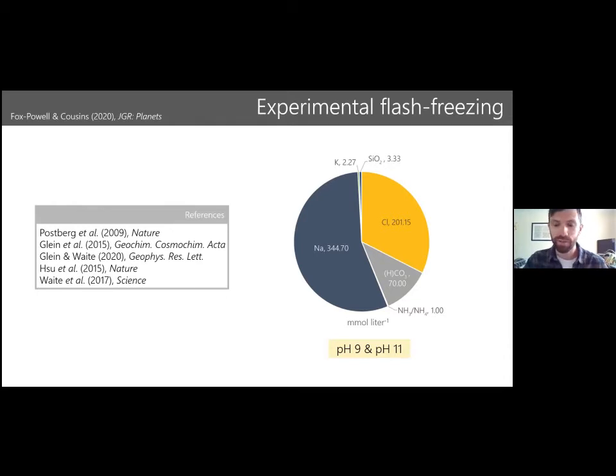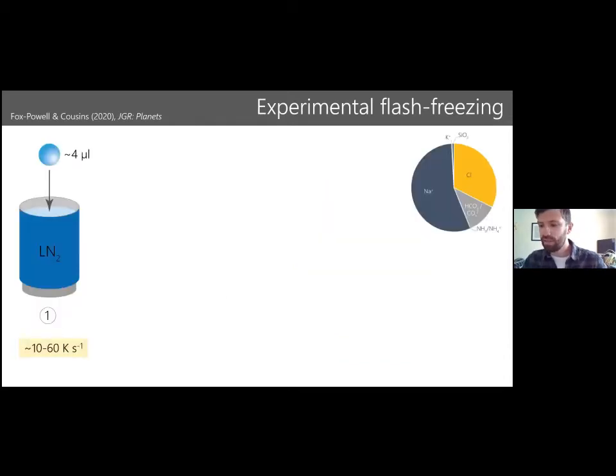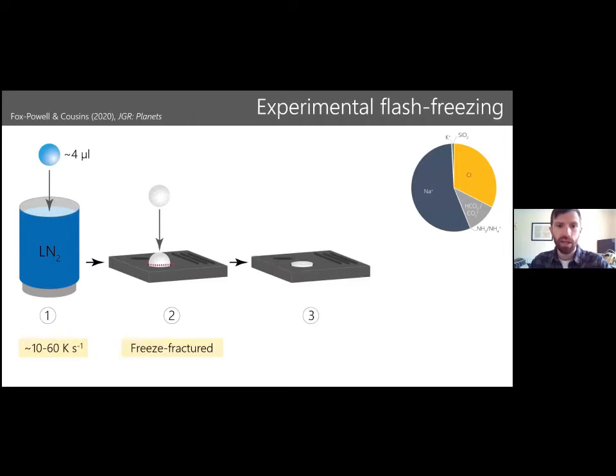Very alkaline fluid. What we did is freeze droplets of this fluid in liquid nitrogen. This produces a cooling rate of around 10 to 60 Kelvin per second. These frozen droplets were then mounted on microscope stages and sectioned open. And then we were able to analyze the cut face using cryo scanning electron microscopy.